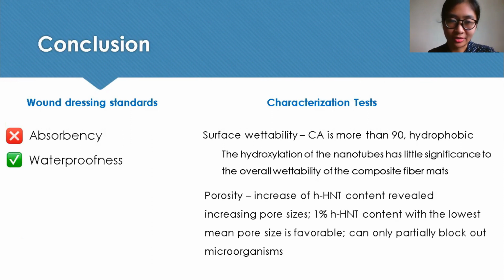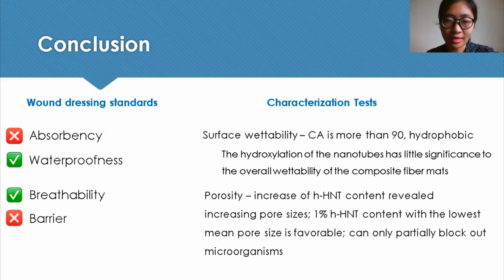Due to the porous nature of the e-spun material, it can allow air to pass through to give breathability to the wound surface. But it is still limited, as it cannot absorb excess wound exudates, and it cannot totally block out all microorganisms due to its bigger pore sizes; it can only partially block those microorganisms out. So although the fabricated PLA HHNT composite mats did not possess sufficient properties as a wound dressing, the data shown here have significant importance that can aid in further tuning the properties of fibrous biomaterials.